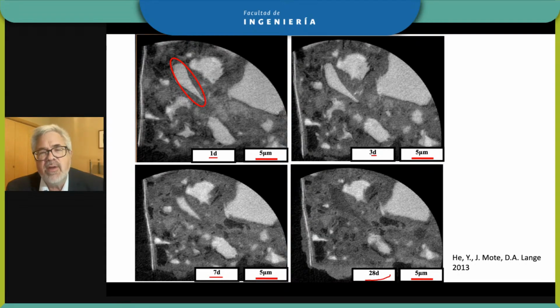And it's not the same with every phase. So this is one particular kind of cement phase, and the others are different than this one. Look at this area. This is an area of original porosity. It's open. At 1 day, it's open. It fills up. At 28 days, it's solid. So we have the other example. Here, just to complete my cases, we have a grain over here. By 28 days, it's still there. So we have some phases that are relatively inert and are not hydrating to create new product.